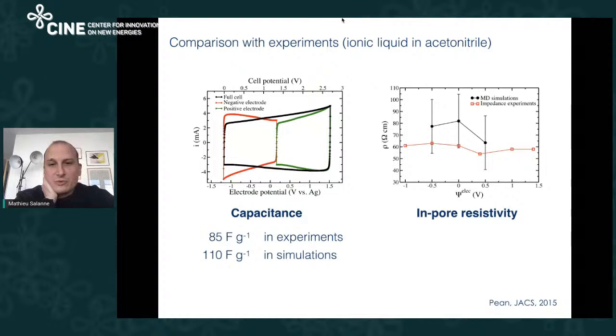And we could also compare the resistivity. So this was extracted from impedance, as was shown in the previous talk. The impedance gives access to the internal resistance of the system. And from simulation, it's also possible to compute this resistivity. And you see that here again, we have 20% difference between experiment and simulation. And this shows that the dynamics of the ions are also well reproduced from the simulation. So this is very important because we are quite confident that our models are realistic. They are not perfect, we know there are limits, but we are quite confident that they give a correct picture of the structure and the dynamics.